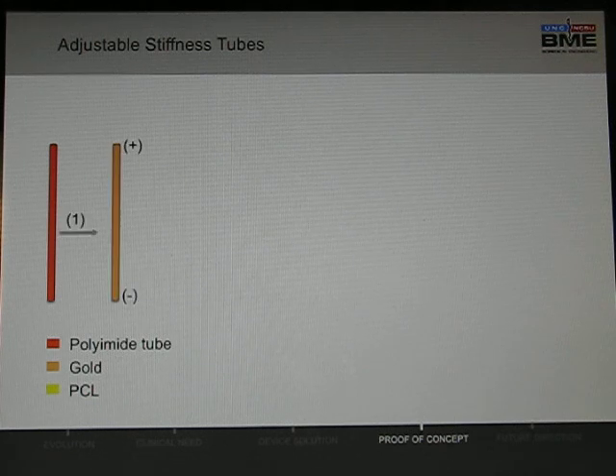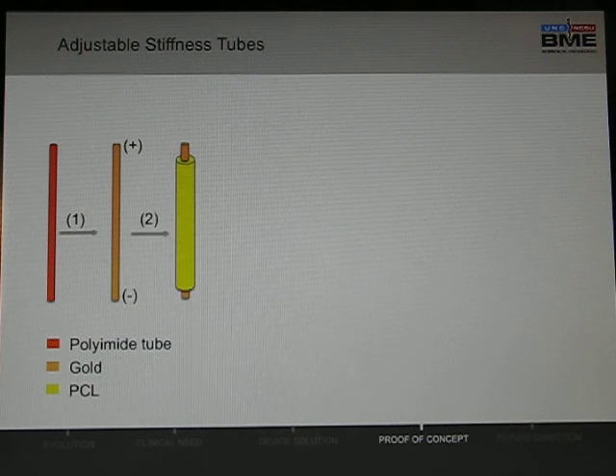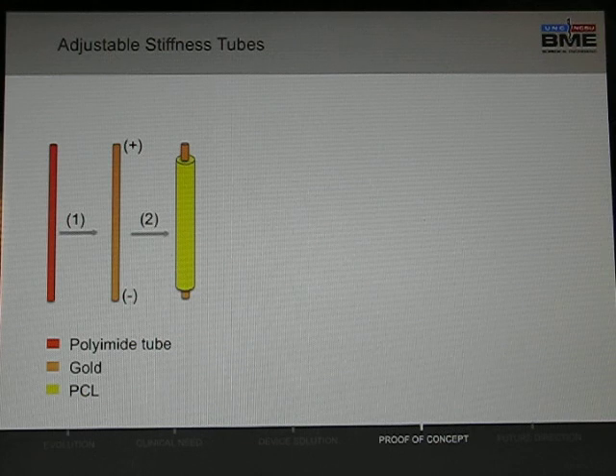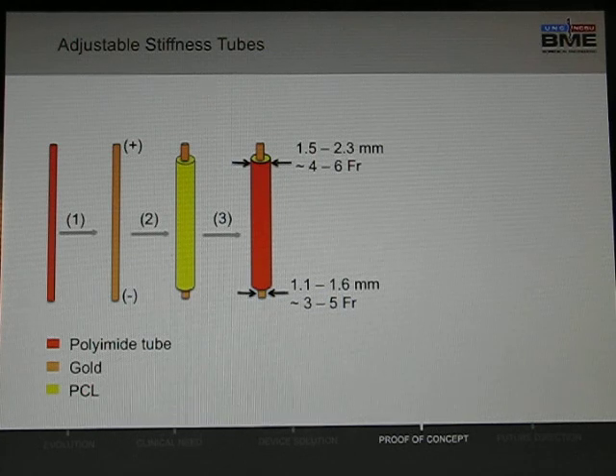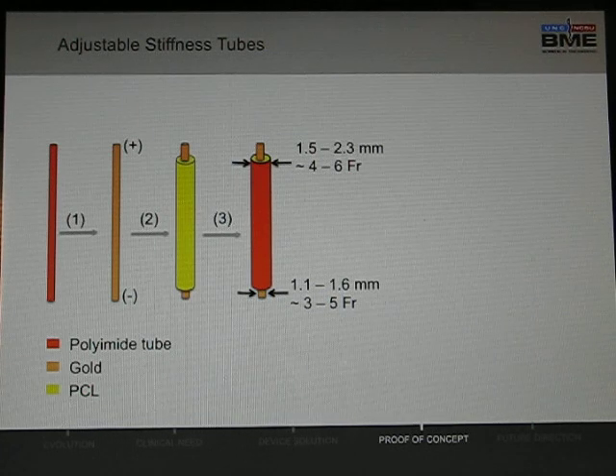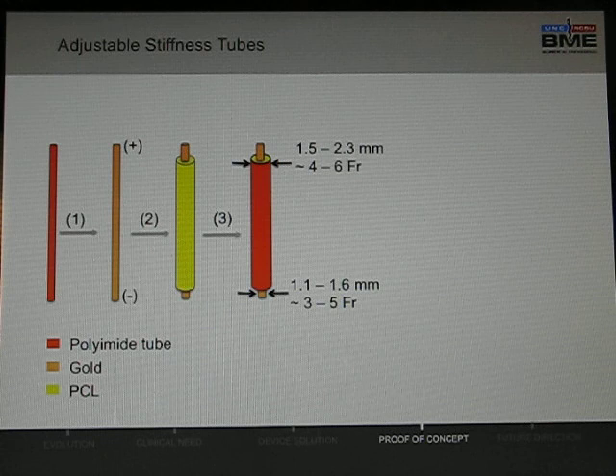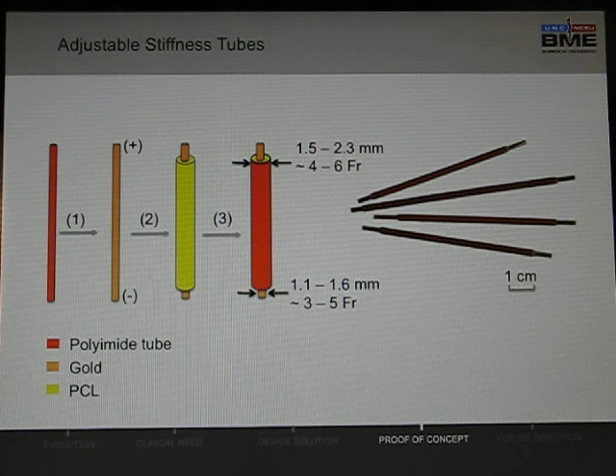Evaporate a thin film of gold, in this case acting as the conductive element. Deposit the PCL. And housed it inside a larger diameter polyimide tube measuring the following dimensions. And here you have the physical embodiment of the adjustable stiffness tubes.